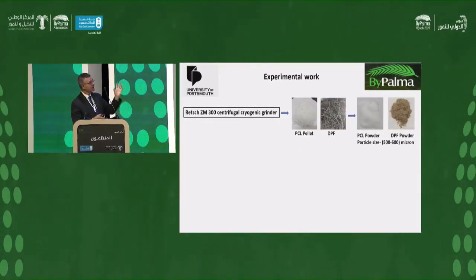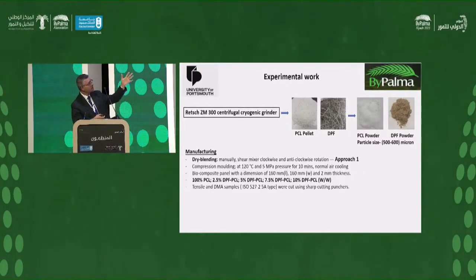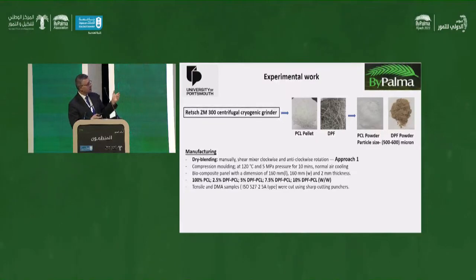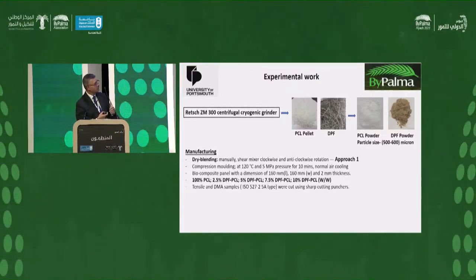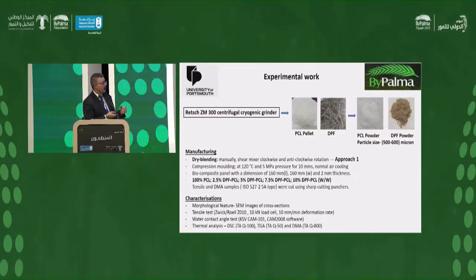You can see PCL pellets and date palm fiber. PCL is made into powder, as is the date palm fiber. We use this cryogenic grinder to grind them, and then dry blending. Then we use compression molding at 120 degrees, 5 megapascal compaction pressure for 10 minutes, and then normal air cooling, giving a biocomposite panel of that dimension, with different concentrations of date palm fiber from 2.5 to 10 weight percent. We look at tensile properties as well as dynamic mechanical analysis. We also did morphological analysis of the fracture surface of the specimens using SEM, and tensile testing. We also looked at wettability using contact angle measurement, and used DSC and TGA to measure thermal stability.